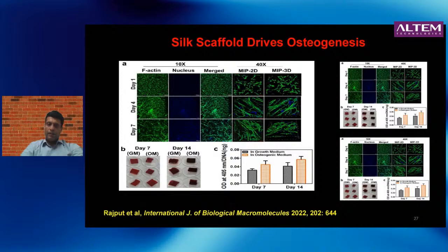And if you look at their ability to deposit calcium phosphate, which is the ability to form bone, then you find that it increases from day 7 to day 14. Further, if you add in soluble factors like osteogenic media, that is actually more intense, which we believe arises because the silk fibroin itself is a good matrix for the bone cells to grow. And by tuning the stiffness to 15% silk fibroin, we found that that was the optimal condition for the bioprinted scaffolds where the bone cells can grow well.